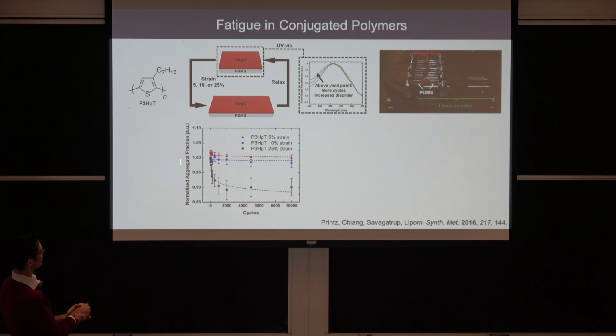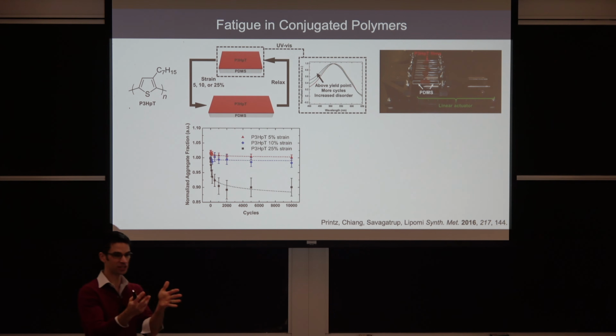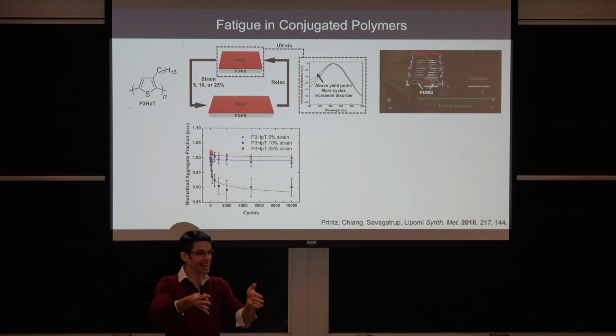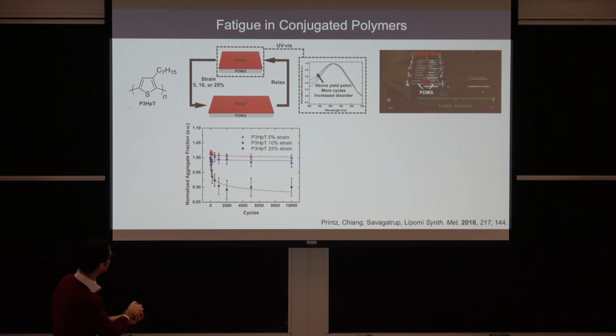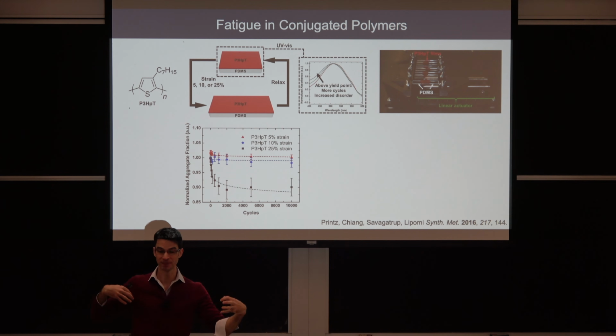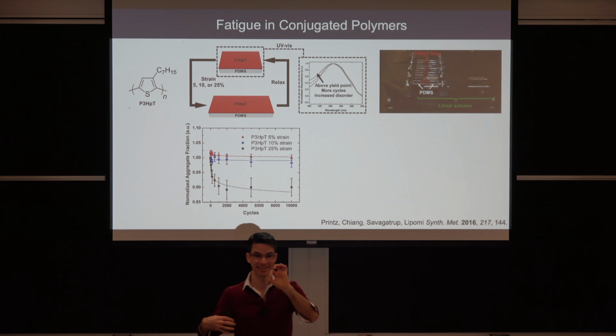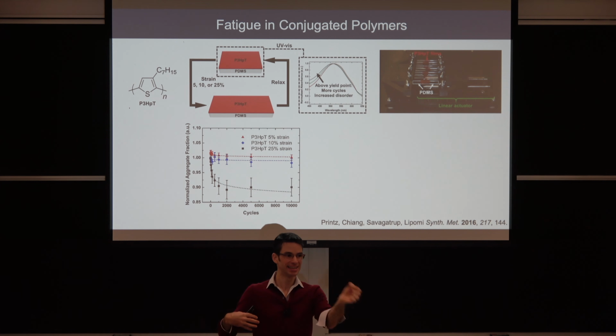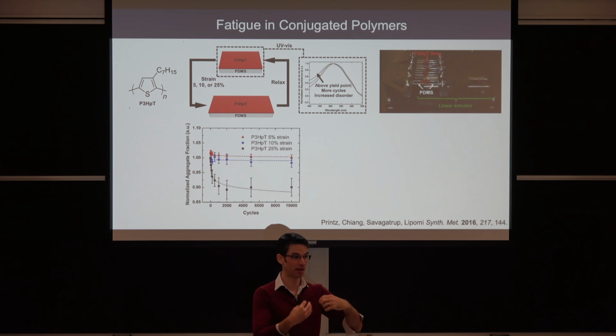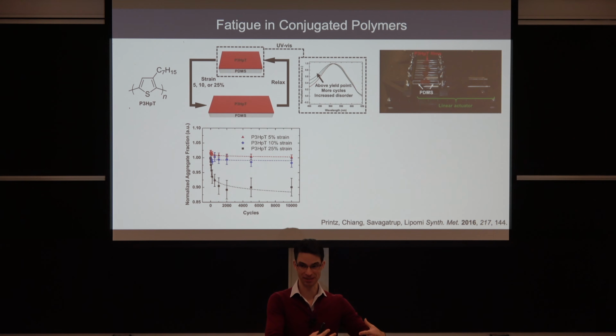And then you plot the aggregate fraction, so the fraction of the chains that are in these pi stacked aggregates, goes down as you keep cycling the material. So this is at 5% strain, 10,000 times, 10% strain, 10,000 times, 25% strain, 10,000 times. As you stretch this material over and over, you're pulling these aggregates apart. It's a little bit like taking the top of a tic-tac box and bending it over and over and over again, and you're changing the microstructure of the material, and eventually it will snap off.